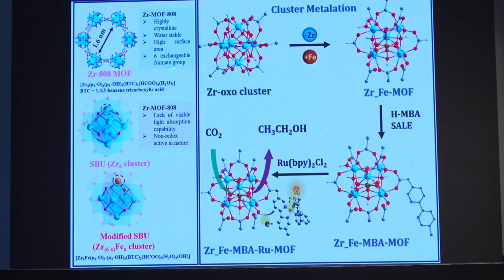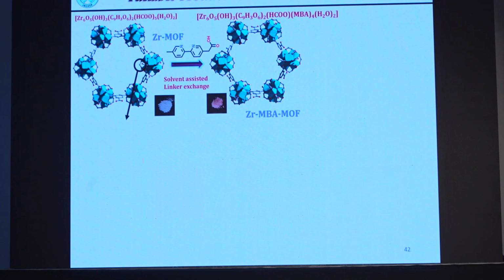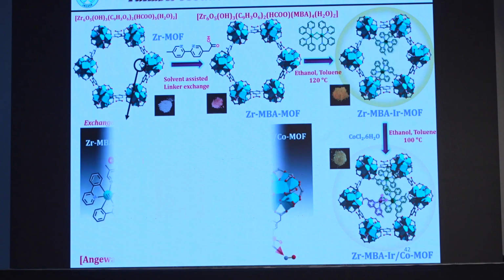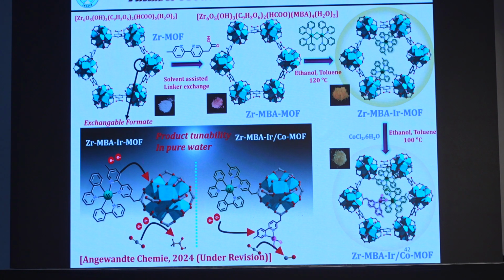So from this, you can get the liquid product. From this, you have the 8 to 12 electron process. So then you have, again, instead of the ruthenium, can you take the iridium here? So with the iridium, again the basic coordination chemistry, iridium 3 plus, because of this your delta o is very, very high because it is the 3 plus charge compared to the ruthenium.